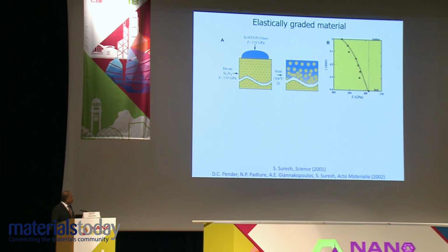Nitin and I had a number of joint students who were looking at ways in which we can create an elastically graded material that had no plasticity. So here is an example of a particular system. We take fully dense silicon nitride, and then we take silica glass on top of it. We melt the glass, and we can dope the glass in such a way that the coefficient of thermal expansion of the glass is very similar to that of silicon nitride. When you melt it, the glass diffuses into the silicon nitride substrate.